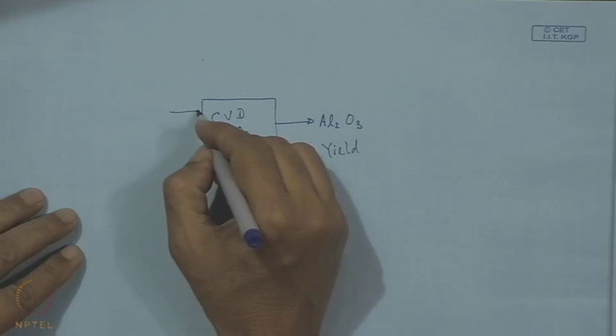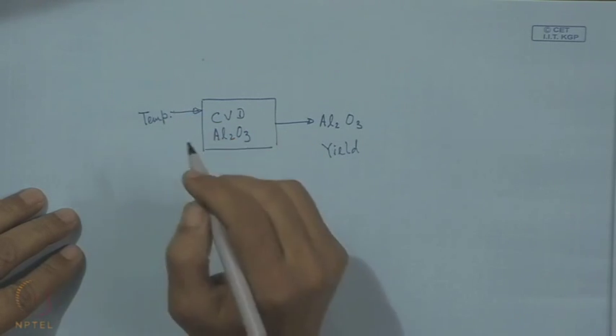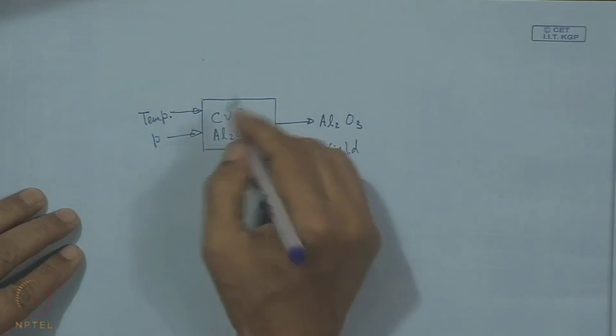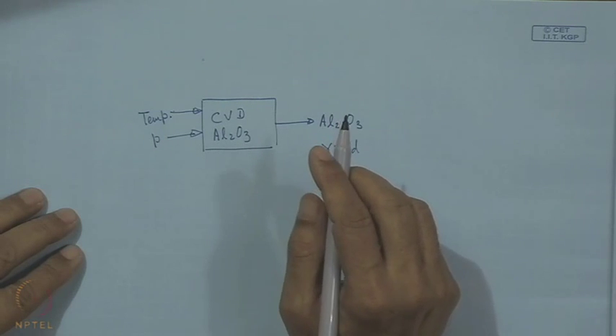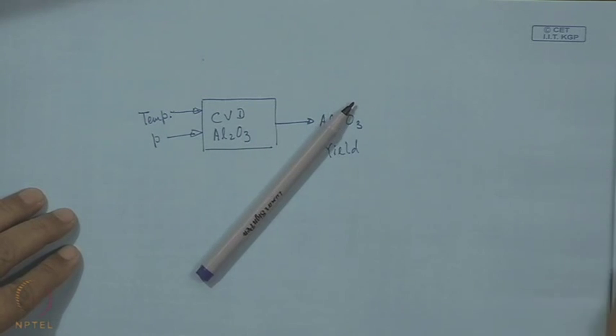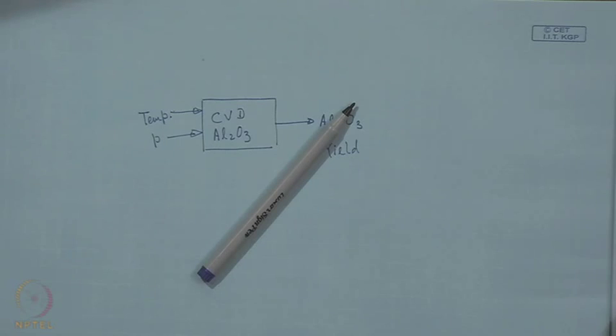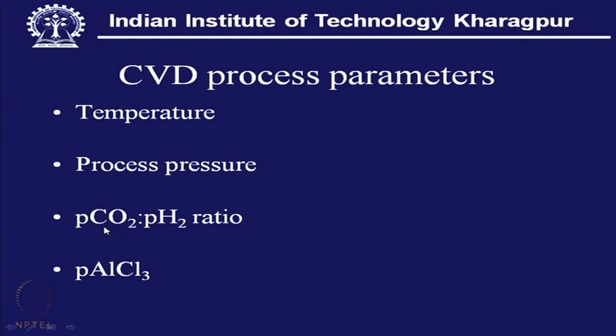But on this side, the process parameters one can look at are the temperature, then process pressure. These are the two things one should look into. However, in addition, since we have already noticed that carbon dioxide, CO2, and hydrogen are admitted in the reactor maintaining certain temperature and pressure, at the same time we have aluminium trichloride vapor which is continuously generated and admitted. So, all five are the process parameters which can have a dictating role in providing the final outcome, that means the Al2O3 coating yield.